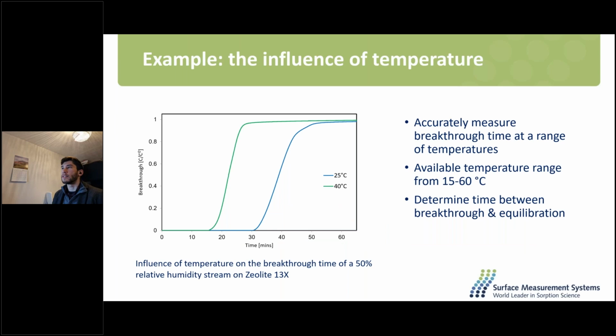Just a quick example. These are just 2 breakthrough curves recorded at 2 different temperatures, just to see the influence of temperature on the breakthrough time at 50% relative humidity. So we can see as you increase the temperature, the kinetics are much faster, so everything breaks through earlier. And also, as you increase the temperature, 50% relative humidity corresponds to more water in an absolute way. So it not only happens faster, but also there is more water coming in. So the breakthrough time is halved.